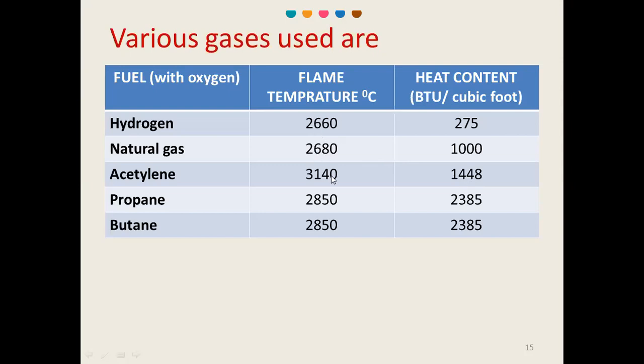it is again not used because, if you see in the previous picture, you are seeing the different zones of the flame. So there is a temperature difference of more than 100 degrees Celsius in each of the different zones of the flame. So it is very difficult, or very critical, to keep the flame at one zone during this procedure, because of these differences in temperature in the different zones by more than 100 degrees Celsius. The next is the propane and the butane gas. You can see they have the same flame temperature and the same heat content, and the heat content is the highest of all those three gases.